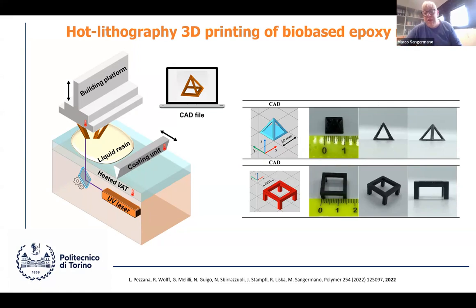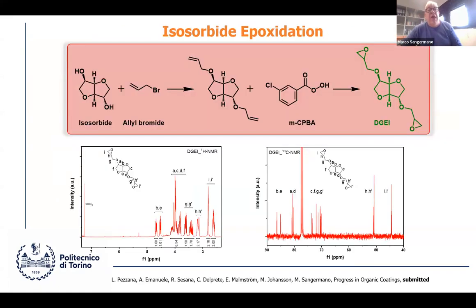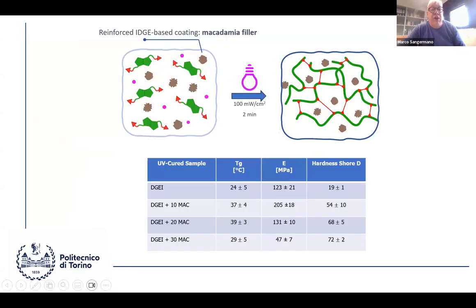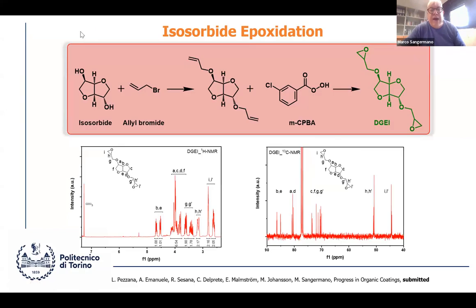In the case of isosorbide, again derived from cellulose, we induce another easy functionalization reaction, so at the end we again have epoxy groups in the chemical structures. Those molecules are characterized by NMR analysis so that we are sure about the structures. These are liquid monomers, which are polymerized under UV light.